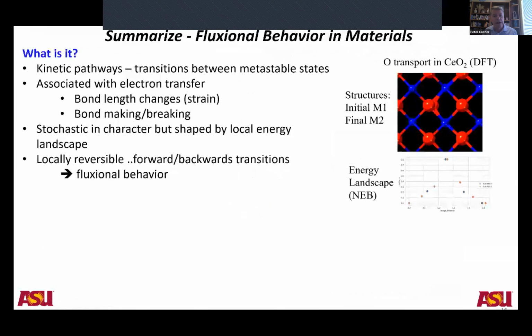So to summarize what we mean by fluxionality, it's, if you will, kinetic pathways, meaning the transitions between different metastable states in the system. It's associated with electron transfer. So what we typically see is bond length changes, strain, or bond making and bond breaking. This, of course, is stochastic in character, but generally shaped by the energy landscape. And of course, the processes that we're looking at are reversible, so you can imagine things jumping forward and backwards. And so we get a superposition.